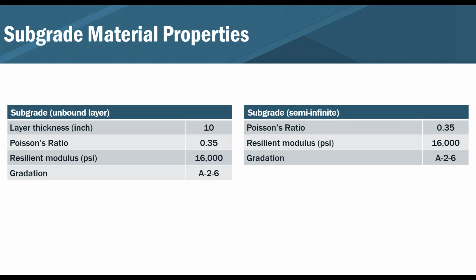On the subgrade side, again, we had to take off that top 10 inches of the subgrade layer so we can get the PMED to run, but you can see that everything is exactly the same. Really, it's just 10 inches. Poisson's ratio is the same as the subgrade. Stiffness is about 16,000 psi, and then it's an A2-6 soil. So again, that's just to get the program to run, not necessarily that you're actually building a separate layer.